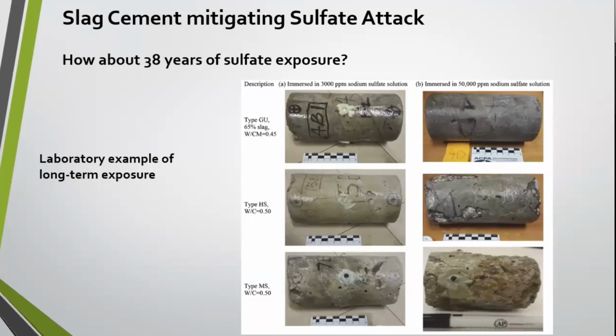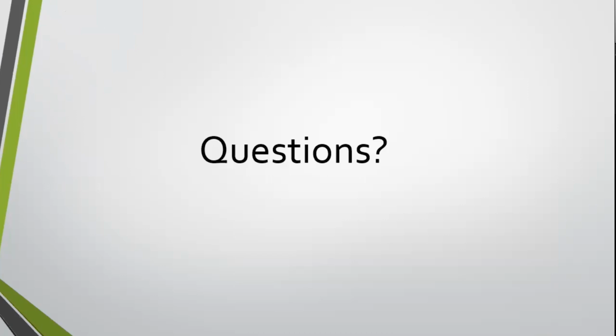So again, moderate sulfate resistant cement used on the bottom 2, high sulfate resistant cement used on the middle 2, and then at the top we've got a general use cement, but we're using a 65% slag replacement. And you can see after 38 years of exposure, just how much resistance to that sulfate attack the slag gave us in this case. And so I believe that is the last slide that I've got, and I will open it up to questions.